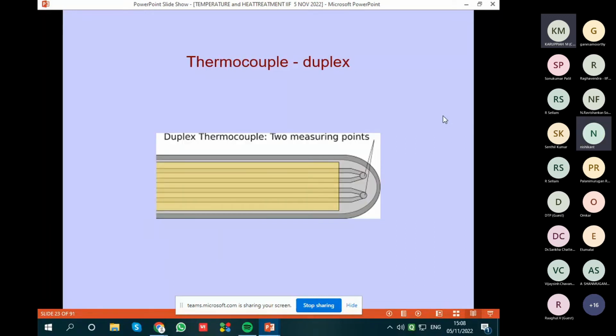If you're using a duplex thermocouple, there are some other problems. For any duplex thermocouple, there are two junctions inside. If they are not constructed properly, at high temperatures, they start giving problems. At lower temperatures, they work fine. But as the temperature rises, sometimes the wires get bent and they touch each other inside the pipe.